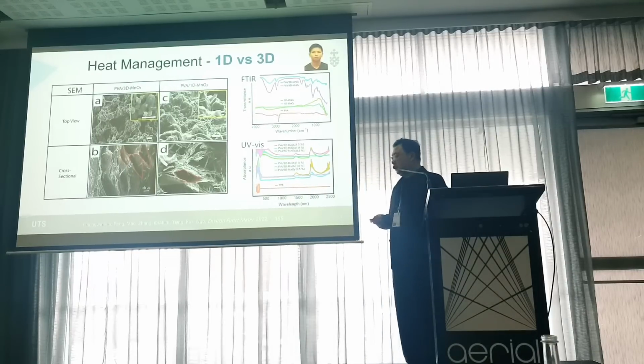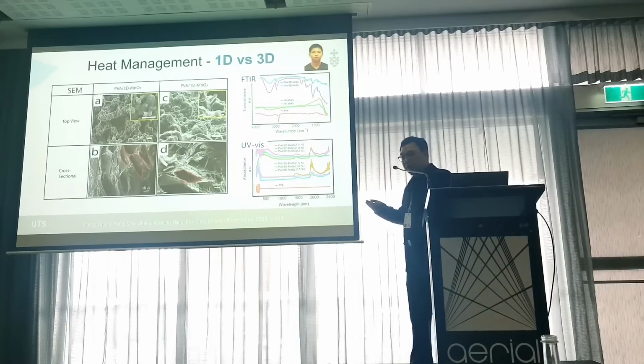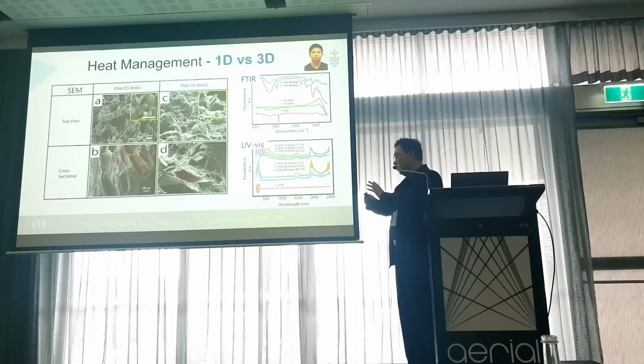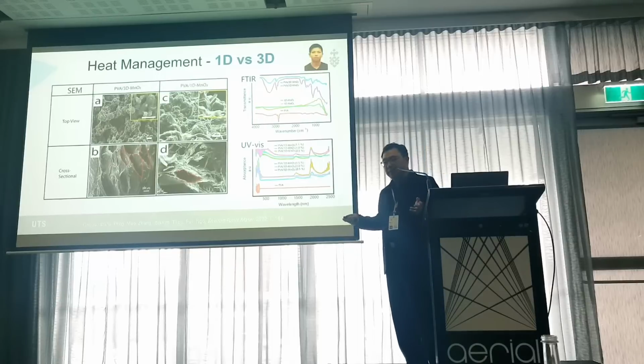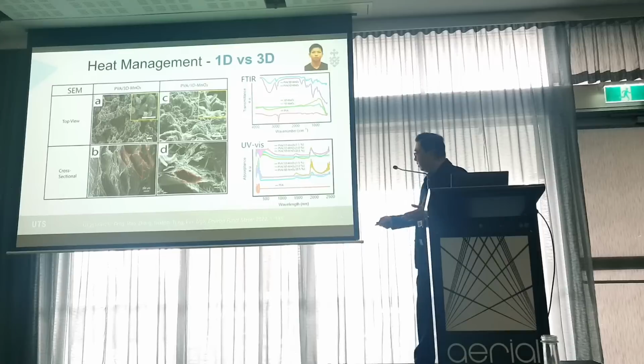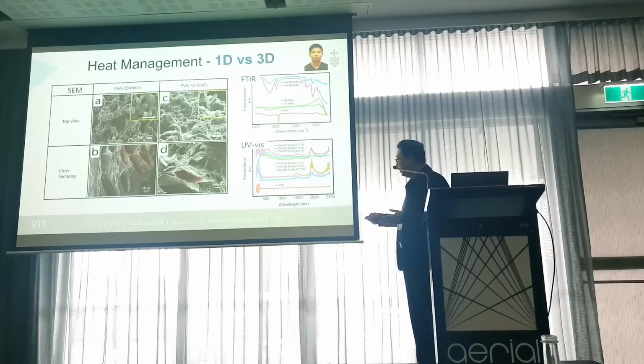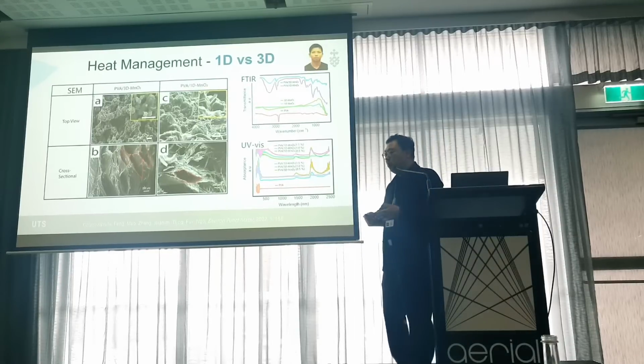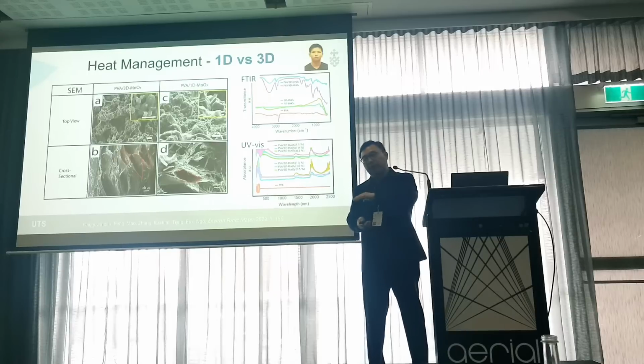And you can see that when we introduce black colored photothermal materials into the hydrogels, they can efficiently absorb the solar irradiation. They usually show a very broad solar absorption spectrum from 300 nanometers to 2500 nanometers. In contrast, the pristine PVA samples, as you can see, have almost no solar absorption above 400 nanometers.